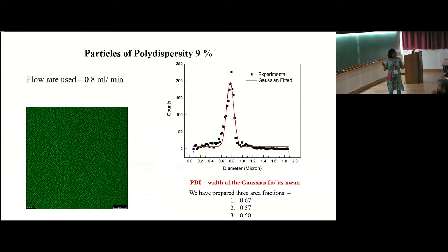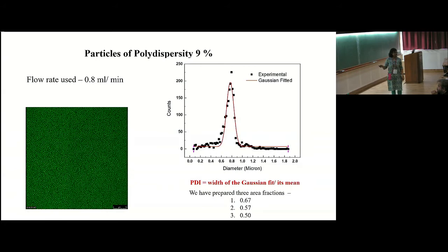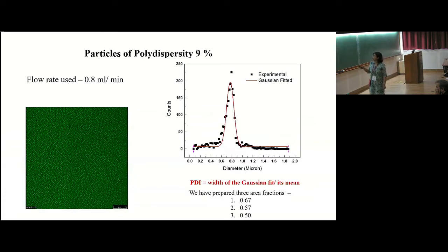So, I don't have a lot of data, just two data points. In the first experiment, where we used a flow rate of about 0.8 ml per minute, we synthesized these particles. The reason why it looks like this is because this is taken under a confocal microscope. So, in addition to the reaction that I showed you earlier, we also had to bind a dye, because you have to use a laser light for the imaging. And if you see these little dots here, they are about 500 nanometers, well, 800 nanometers across. That's the average diameter. And they are polydispersed, but not extremely polydispersed.